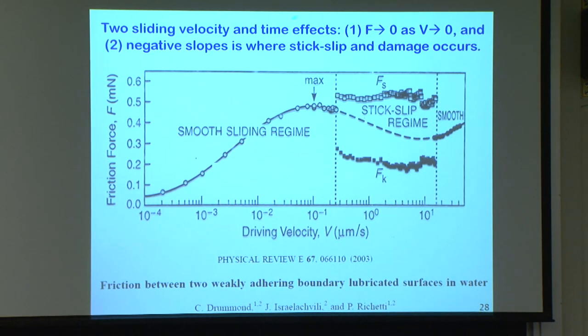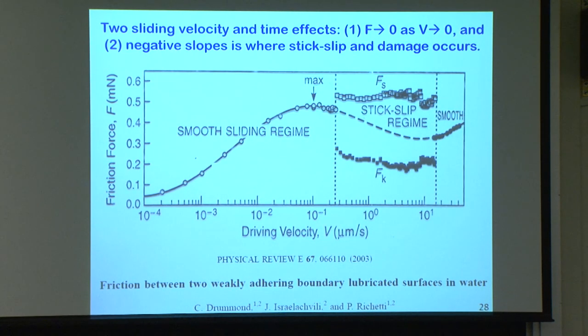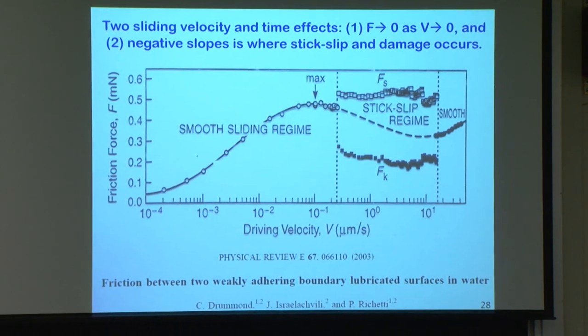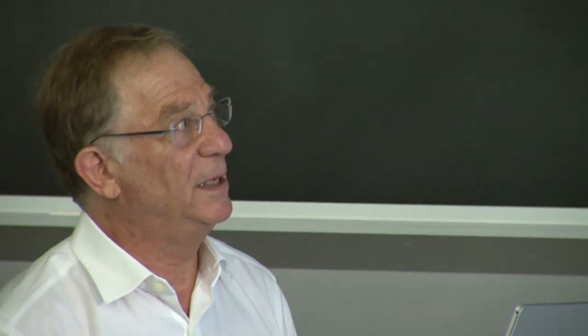And the first thing I want to say, just two important things about friction concerning the sliding and time effects. The first one is that the friction must go to zero as the velocity goes to zero. People often talk about a static yield point or inherent fracture strength. It's a bit like the pitch drop experiment I was showing. Well, actually, if you wait long enough, everything is eventually going to move, whether it's pitch or whatever it is. So really, it's always velocity dependent. And the same for adhesion. If you pull for long enough at a very low force, it'll still come off at a finite temperature at some point. Same with friction.